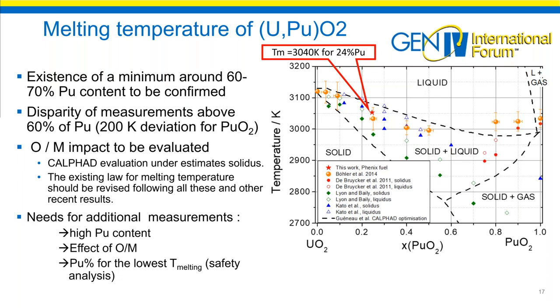With the CALPHAD tool, a thermochemistry tool, we can estimate this melting temperature, but up to now it underestimates the solidus. The existing law for melting temperature should be revised following all these recent results. And the correlation of the melting temperature with the plutonium content and the stoichiometry is really necessary.